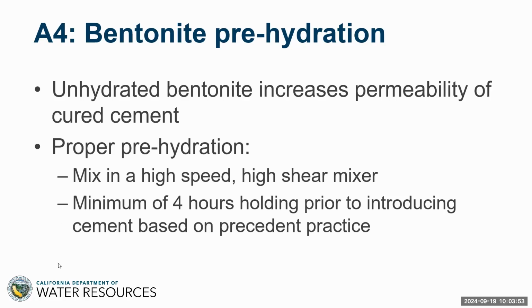So that's why we do two things. First of all, proper prehydration. This is what is really best practice. You mix in a high-speed, high-shear mixer. It'll probably take you a couple of minutes for a couple of bags to go through. Then hold that in a holding tank, agitated or bubbled, just to try and keep the whole thing going. And that should be kept in that condition for at least about 4 hours prior to introducing the cement.